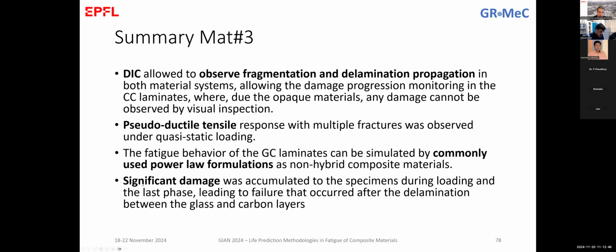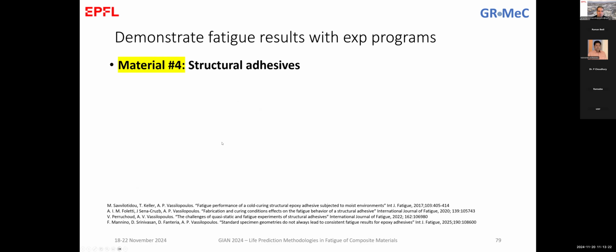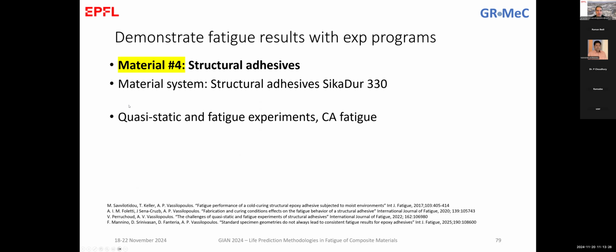And for the specific material 3, which is this hybrid composite, we've seen that we had damage that was initially localized and then distributed to cause delamination between the carbon and the glass fibers. And this is due exactly to the difference in the strain at failure of these two components. One is much stiffer than the other, and when we load, we lose somehow the compatibility between them. So then I will also explain a bit the behavior of structural adhesives. Go fast with these two last materials before the next break.